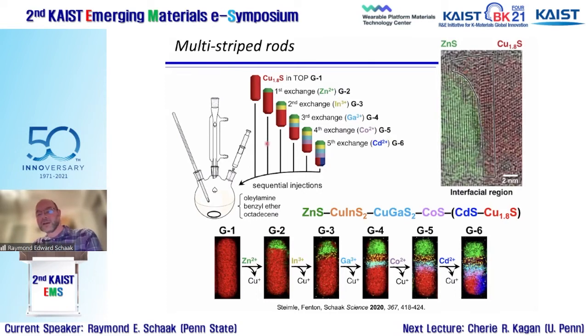These rods are also single crystalline, but when you do that reaction, you end up getting a region between the copper sulfide that remains and whatever the most recent material that was exchanged in. It's got lower crystallinity in this region. And so there's this interfacial region that effectively facilitates the next exchange reaction, or at least ends up contributing to where the next segment will go. And so all of that said, the order in which you choose to inject your exchange solutions becomes the order in which they exchange sequentially in the rod.